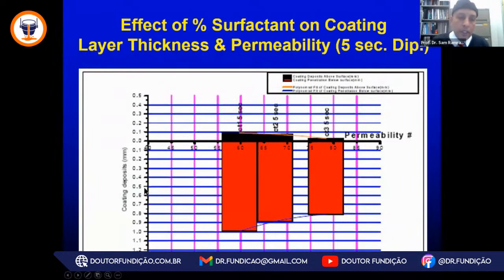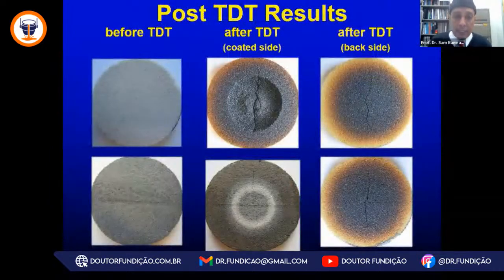So here we are showing the nominal deposits of the coating above the surface, below the surface, and then we measure permeability for these specimens. We can tell that, yes, it's logical. The coating thickness is related to permeability. So for the same sand binder system, we can see how that proud layer or that penetrated layer can retard the venting characteristics of the sand binder system in the casting process.